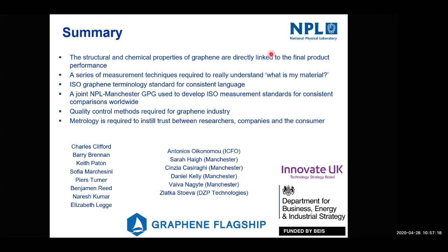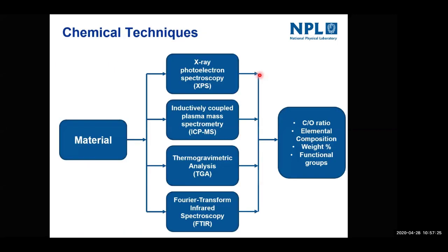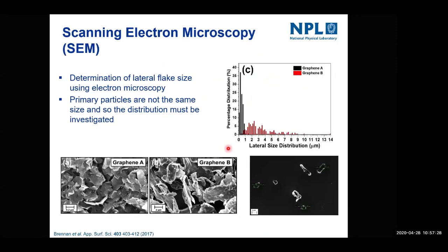If you think back, sorry, I can control the slides here, I think. If I try and go through, if you think about the distribution here, the median values of these two distributions will obviously be different. But then also, by looking at the full width at half maximum as a kind of distribution here, you'll see that there's a very different range, and that will come out essentially by looking at the standard deviation from the mean here. So that is what you would do when you've got hundreds of measurements, and you can do that with AFM. But otherwise, if you're relating the thickness to the lateral size through AFM, then you would essentially take the range that you see in lateral size and calculate it for the thickness as well.